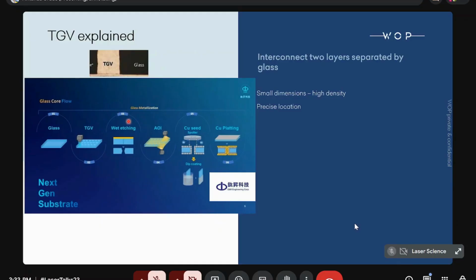Then we check with automated optical inspection and give it to metallization, where a seed layer is set on the surface and inside of the via, and copper is put into the via. Afterwards, of course, it should be removed from the surfaces.